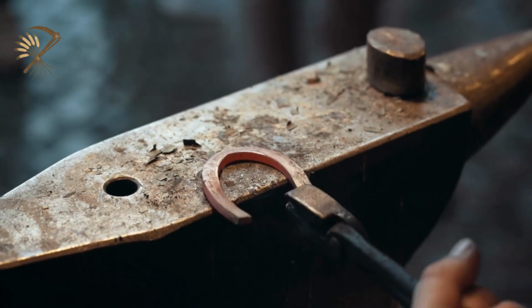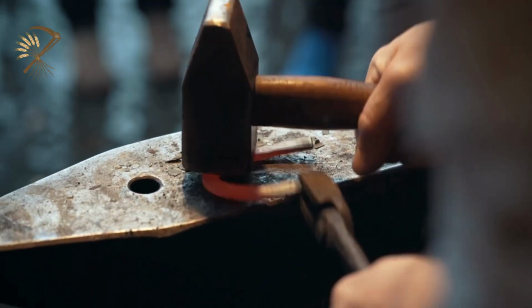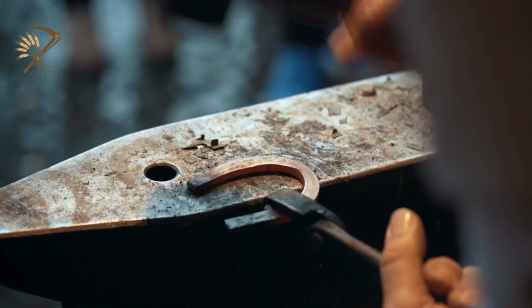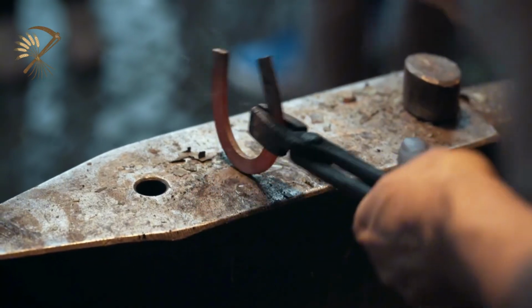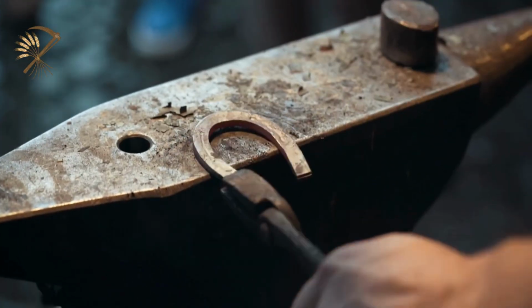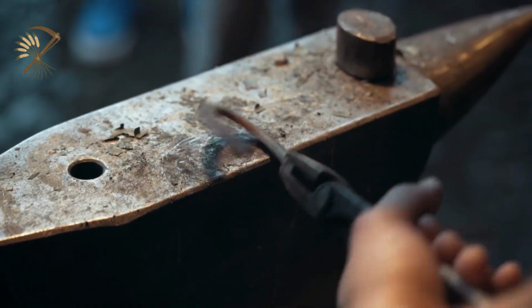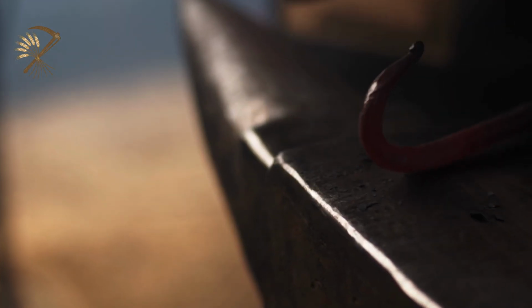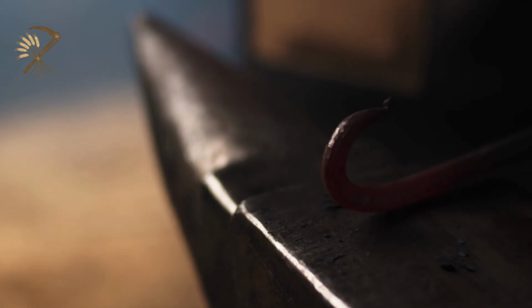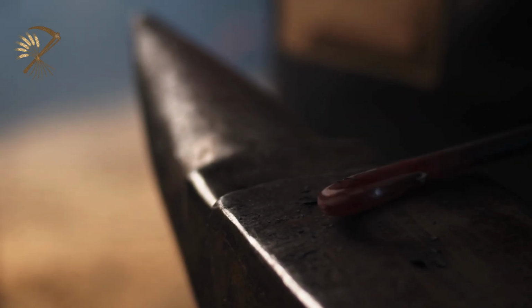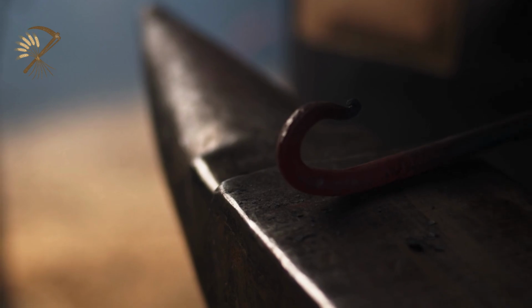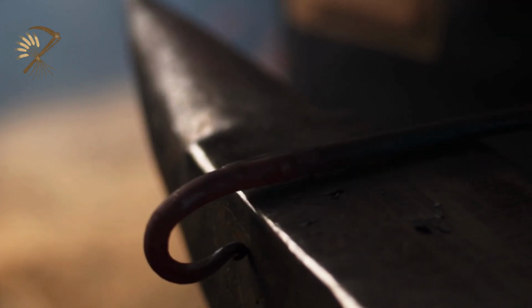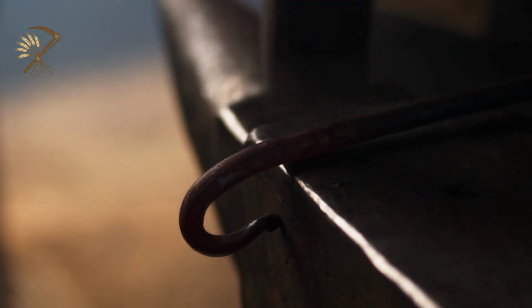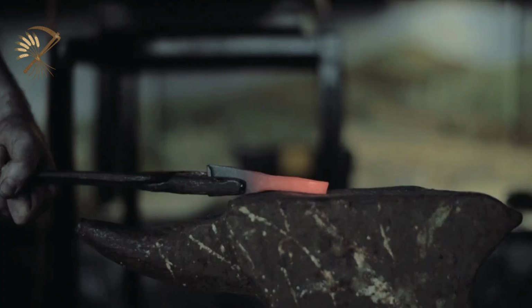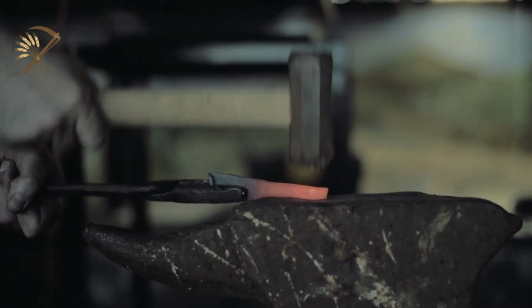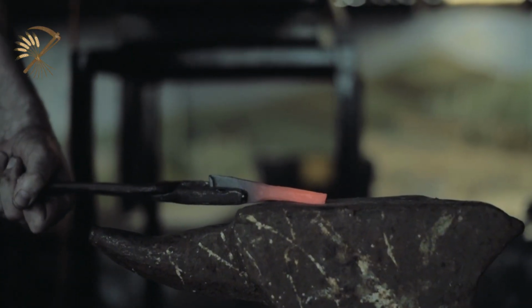The carbon content in steel determines its hardness potential, edge retention, and overall performance. High carbon steel with 0.8 to 1.05% carbon can be hardened through heat treatment to Rockwell 58 to 62 HRC, hard enough to hold a sharp edge through hundreds of hours of use. Low carbon steel at 0.18% cannot be hardened effectively regardless of heat treatment, reaching only Rockwell 25 to 30 HRC, soft enough that edges dull within hours of use.